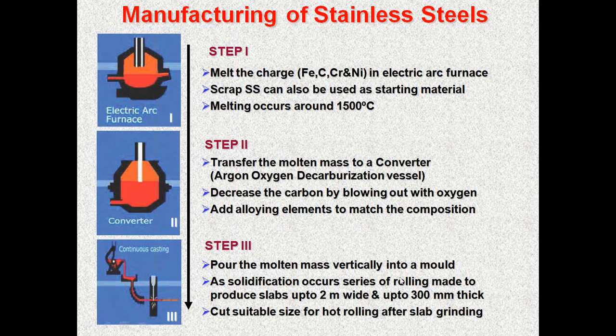And you can also do continuous casting, then rolling them up to 2 meters wide and up to 300 millimeters thick. You can then use a special setup for hot rolling, and this can be done after slab grading. This is a very simple process. Step 1, make the primary melt. Step 2, it is again treated with the argon oxygen decarburization process to adjust carbon and other alloying elements. The third step is making it into a wrought product.